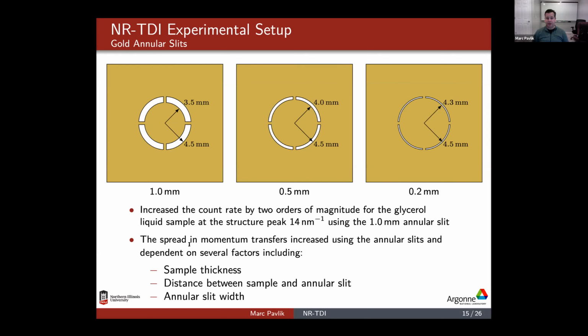Unfortunately, when we use these annular slits, because of the way the geometry is set up, the spread in momentum, or the delta Q resolution, is increased. There are mainly 3 factors that affect the resolution: the thickness of the sample, the distance between our sample and our annular slit, and the annular slit width itself.